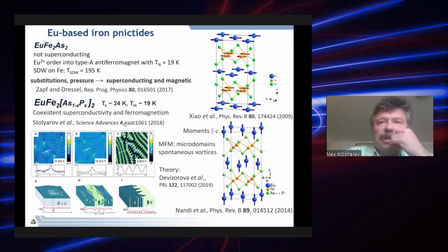It's a very peculiar material. First of all, it's a ferromagnet. Phosphorus substitution leads to a flip of the magnetic moment. It's oriented along the axis, and they show a spectacular non-uniform state in agreement with early theoretical prediction. Namely, the magnet splits into a domain structure, where domain size and shape are very sensitive to temperature. It means that it's joined by superconductivity, and the superconducting state also becomes non-uniform. There are spontaneous vortices generated by the magnetic moment. So it's a combination of two theoretical predictions, theoretically predicted non-uniform states.